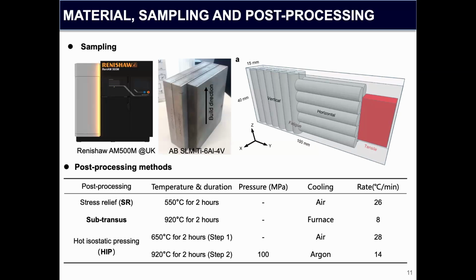use three types of post-processing methods. The first one is called stress relief. The process temperature is 550 degrees centigrade, and the duration is 2 hours. The second one is called subtransus. The temperature is elevated to 920 degrees C, also for 2 hours. And the other one is HIP.